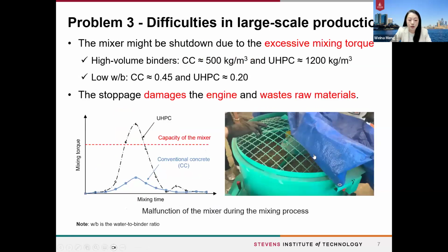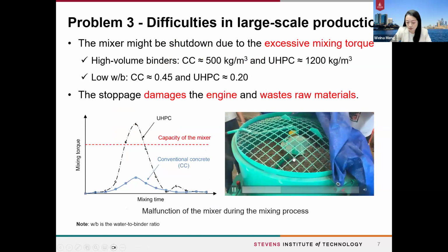So the third problem we have here is the difficulty of large-scale production of UHPC. As you can see, usually during the mixing, the mixer will be shut down if you mix a large volume of UHPC. But it's really not the case for using the normal mixer to mix conventional concrete.